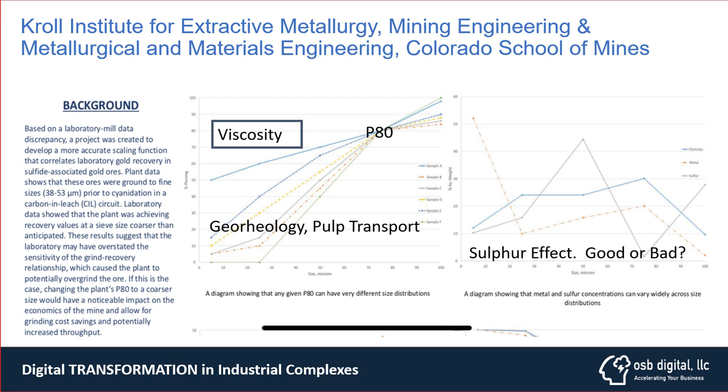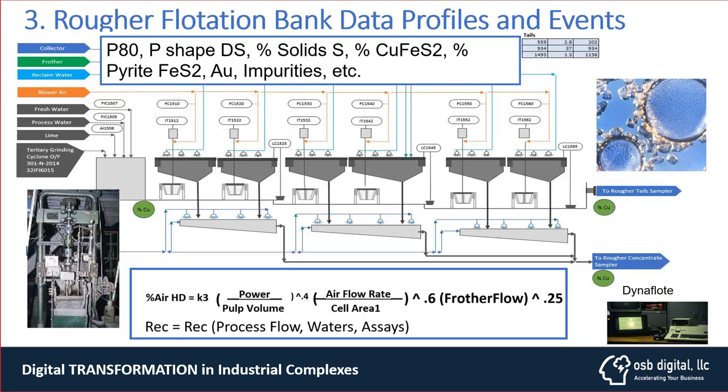That size distribution is critical because these days, due to changes in hardness, it is changing, and that changes the viscosity, which defeats the capabilities of traditional grinding systems, causing roping in the cyclones. Of course, that coarse or fine material also affects the pulp density in the flotation, creating rheological problems in flotation, as we have been studying recently with the available froth cameras.